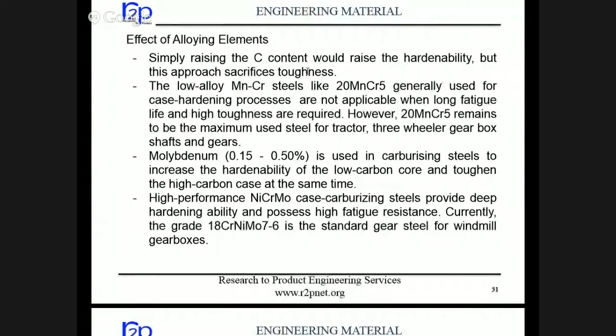So whenever we need a tough core and harder case, then we need to add the alloying element. This is the low carbon steel, plain carbon steel, you can say. Then in case of manganese chrome steels like 20 MnCr5, these type of case hardening steels are not applicable when long fatigue life and high toughness are required. So in the medium range, you can say in a gear in the primary stage only, where the torque increase has not happened to that extent, we can use 20 MnCr5 or 16 MnCr5.